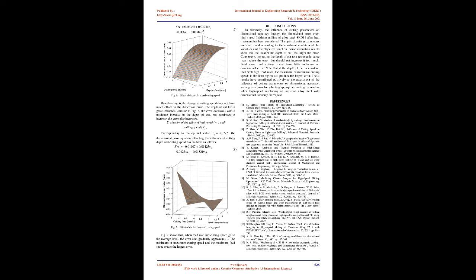Conclusions in summary: the influence of cutting parameters on dimensional accuracy through the dimensional error when high-speed finishing milling of alloy steel SKD11 after heat treatment has been considered. The optimal cutting parameters are also found according to the constraint condition of the variables and the objective function. Some evaluation results show that the smaller the depth of cut, the larger the error. Conversely, increasing the depth of cut to a reasonable value may reduce the error, but should not increase it too much. Feed speed and cutting speed have little influence on dimensional error.